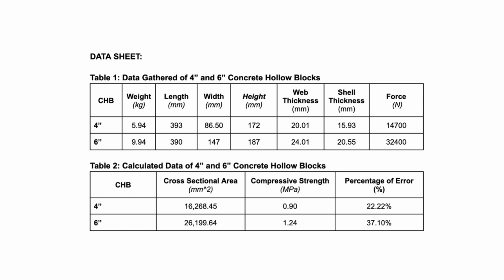ASTM C129-23, respectively. For the 4 inches CHB, it resulted in a percentage error of 22.22%, and for the 6 inches CHB, it resulted in a percentage error of 37.10%. Therefore, we may infer that both 4 inches CHB and 6 inches CHB are unsuitable for load-bearing or non-load-bearing applications due to concerns regarding the block's strength and quality.